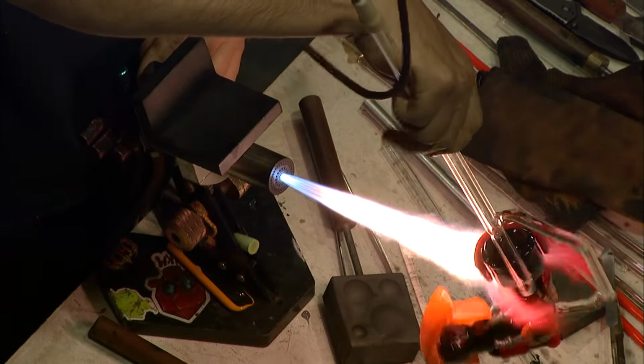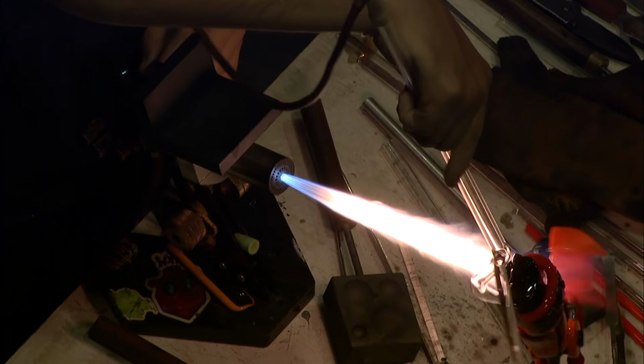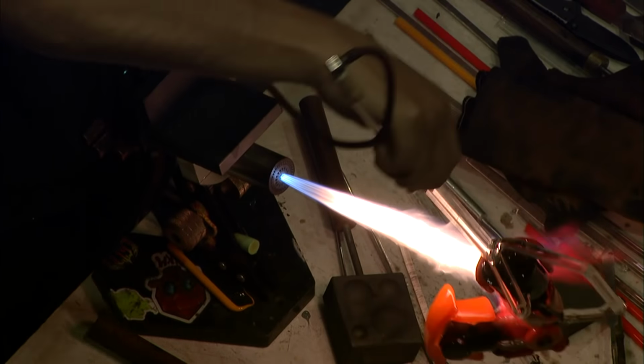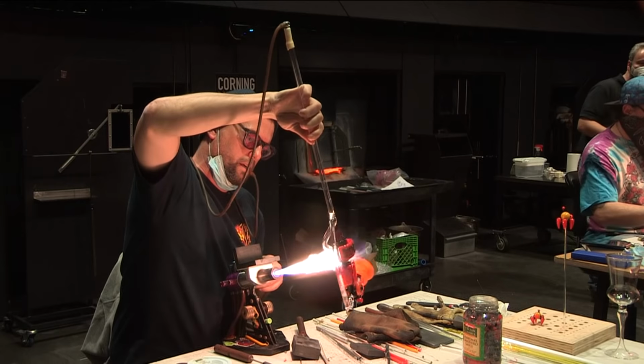When they're pressing down the hollow forms, they do have to consider the idea that air could get trapped in. So if it's a sealed end, they'll tend to start at the sealed end, kind of roll that graphite tool back to squeeze the air out. They've also created some of the flat sheets by just flattening out solid rods of colored glass.